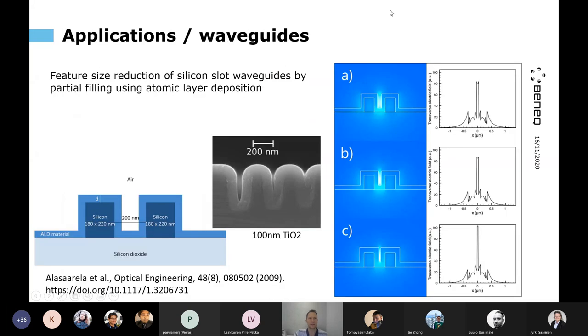Okay. And then I mentioned waveguides already earlier. So there are some things that have been already done for waveguides. Here are some examples. In this case, again, an earlier example, this ALD coating here is used to change the dimension of the slot in this silicon slot waveguide. So by this coating thickness, you can adjust how small a gap is finally left there. And this nice picture here shows that in this case, the silicon substrate had various different sizes of slots to begin with, and then there is a 100 nanometer titanium oxide coating that covers the whole feature.